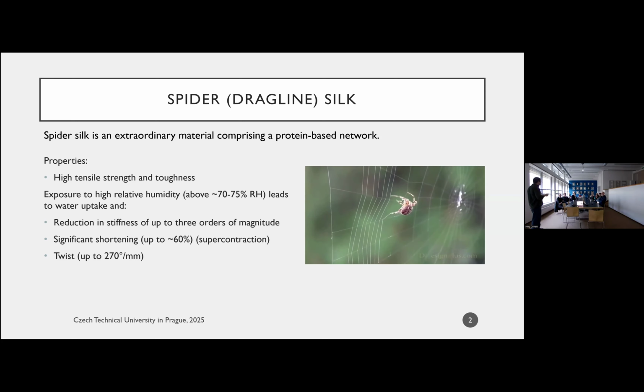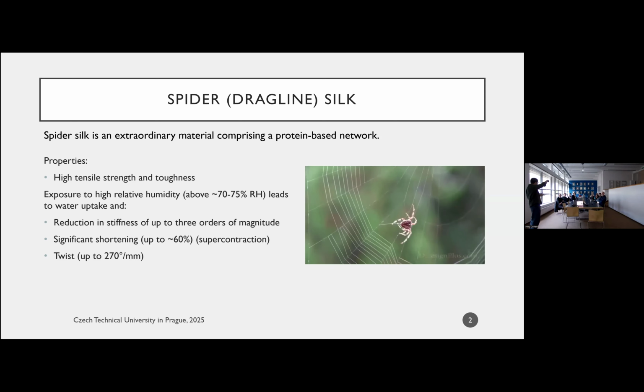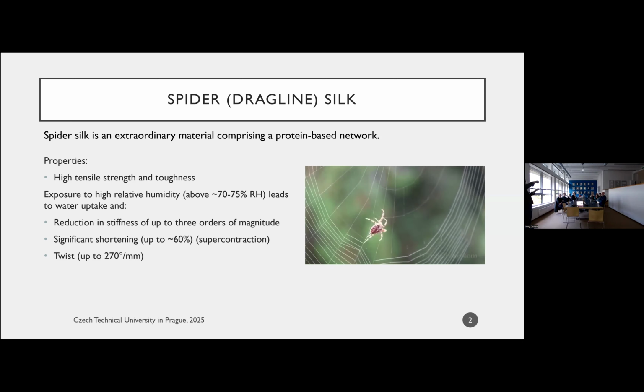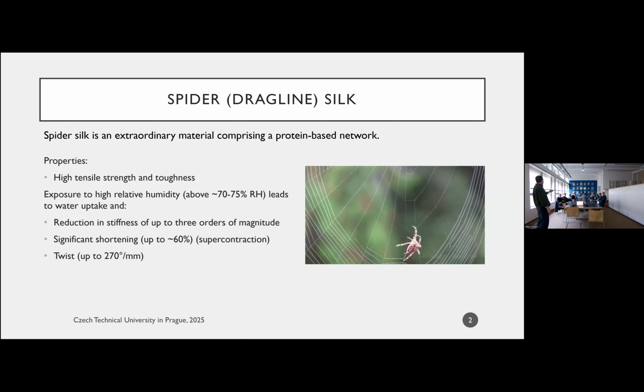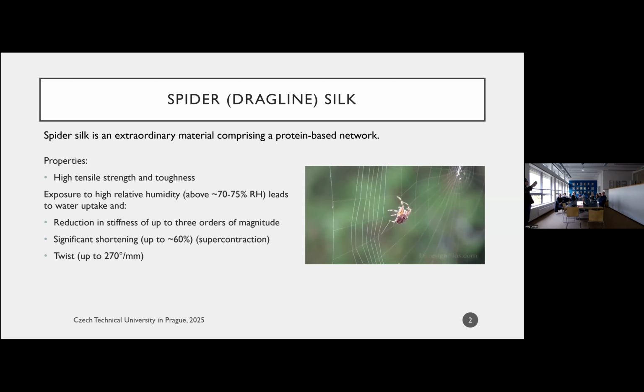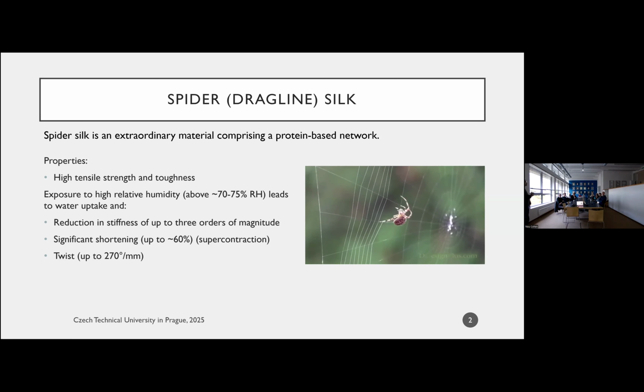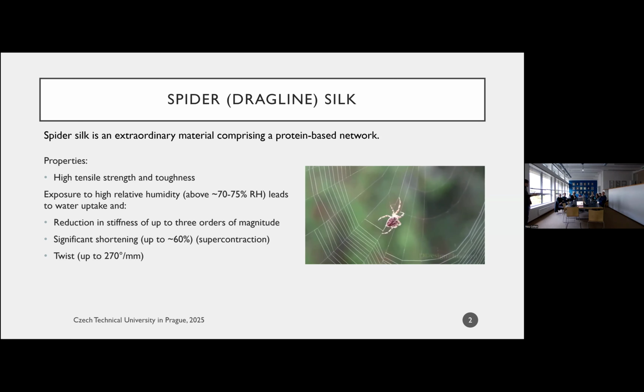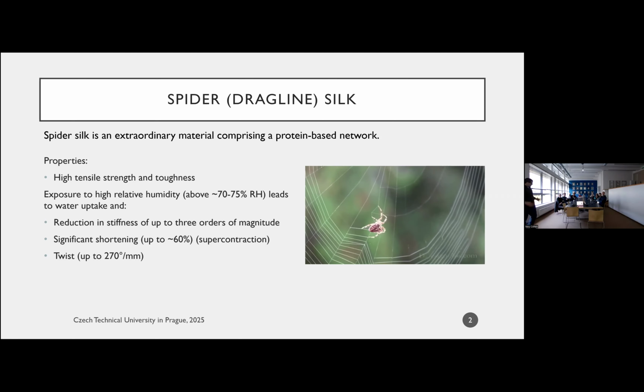The second thing that happens, and this is an even weirder phenomenon, is that if I subject the silk fiber to high humidity, water molecules diffuse into the fiber, and the fiber itself contracts. So it shortens, even though water diffuses into it. It also dilates, but it shortens by as much as 60%. This is often termed supercontraction. And if you've worked on gels, you know this is extremely counterintuitive. You're all familiar with, say, polyacrylamide beads that we call superabsorbent polymers. We put them in water, they swell by about 100 times. Or if you think of diapers, when we subject them to liquid, they swell isotropically. Most of the gels I'm familiar with, besides this one, all swell isotropically. This doesn't. This contracts and dilates.